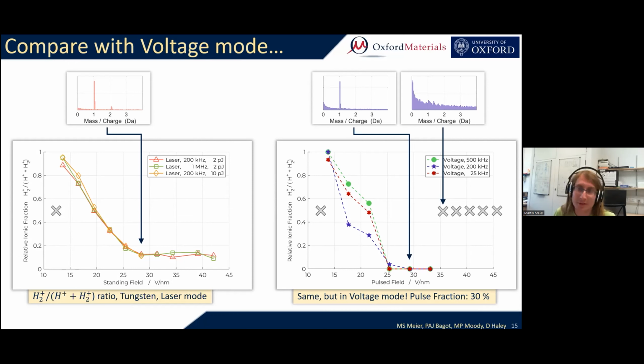A, in voltage mode, given a sufficiently high electric field, there is no contaminant hydrogen left at the tip. Or B, in voltage mode, given a sufficiently high electric field, there is contaminant hydrogen left at the tip, but it all is evaporating off pulse such that we don't detect it in our time of flight spectroscopy. And depending on which of these two interpretations you believe, there are also conclusions that we need to draw for